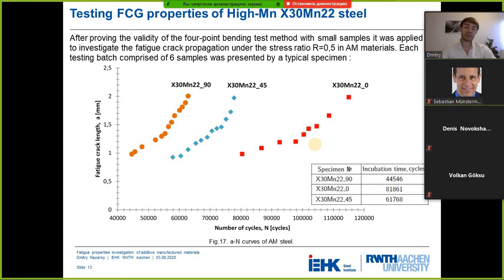It should be said that every single direction was represented by at least 6 specimens, and only one typical specimen was chosen, which represented the whole batch. And here we can see a-N curves from the specimens produced with different building orientations, and it's obviously seen that the shorter incubation time was for vertical specimens, the longer for horizontal specimens.